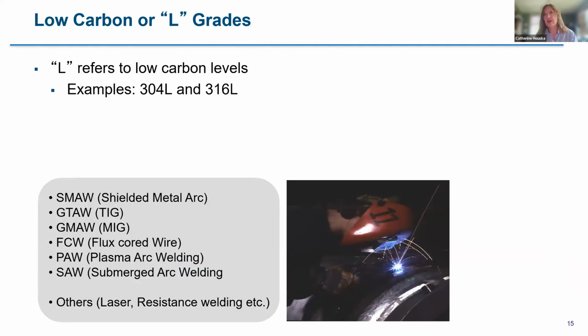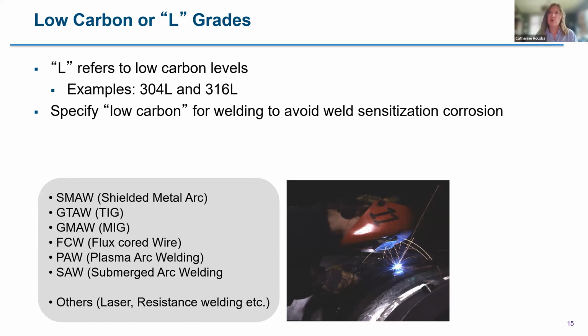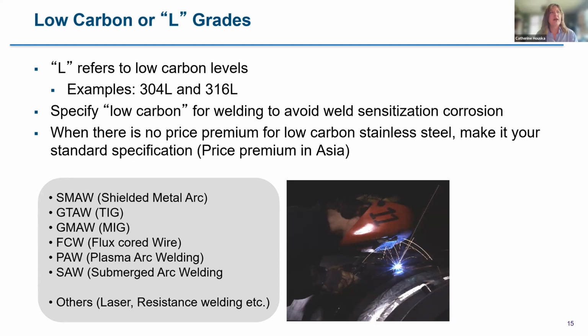So when you see an L, like 304L, 316L in a common name, that means low carbon. That is only needed when you are welding the stainless steel, to avoid sensitization of the weld. That will give you a band of corrosion on either side of the weld if it were to happen. There is no price premium for low carbon stainless steel in much of the world, but I have seen it in Asia occasionally. So it is something to consider. If you're not doing any welding, then you may not need to specify low carbon. In Europe and the Americas, generally you have dual certification of 304/304L and 316/316L.